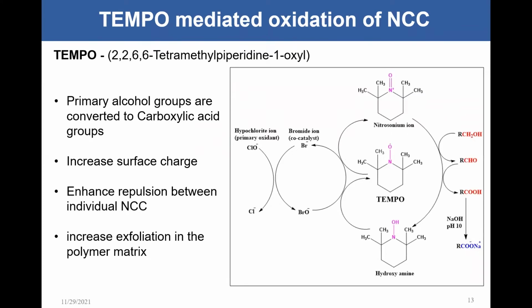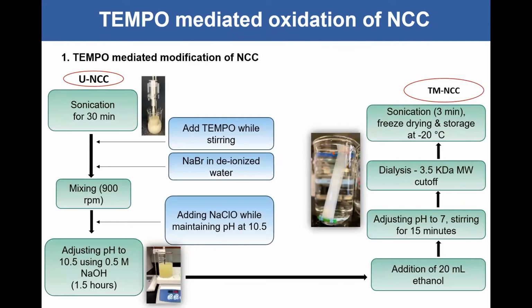So we use a method called TEMPO-mediated oxidation. I'm not going to go into the chemistry of the TEMPO oxidation, but what we basically did was convert the hydroxyl groups, or the alcohol groups, present in the nanocellulose structure into carboxylic groups. When you increase the amount of carboxylic groups on the nanocellulose surface instead of hydroxyl groups, it increases the repulsion between individual nanocrystalline cellulose strands. This helps because when you put it in the polymer matrix, in this case the canola polymer, it helps to disperse it properly, or we call it exfoliate it properly, in the canola polymer matrix.